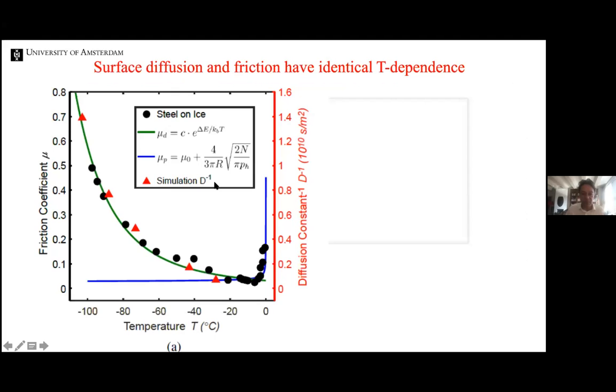And so it turns out that the reciprocal of the diffusion coefficient, which Yuki gets from his simulation, has exactly the same temperature dependence as the friction coefficient, showing that the interpretation of these rolling molecules that lubricate your skate is actually not so very stupid. So this is the friction coefficient in black, the diffusion coefficient in red, and so that actually accounts for all the low temperature behavior in quite a satisfactory way.